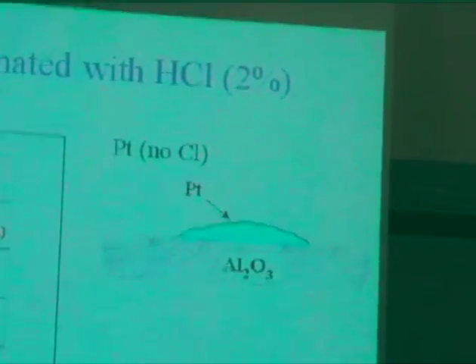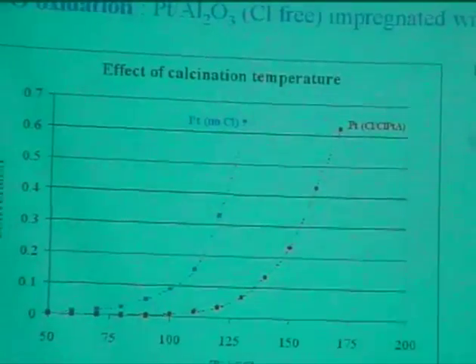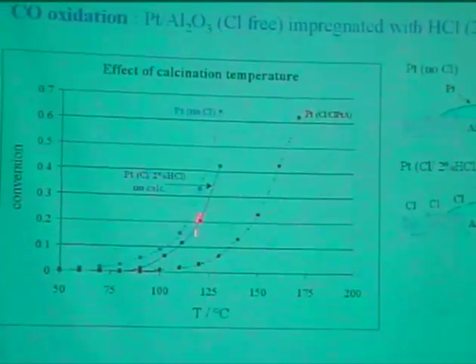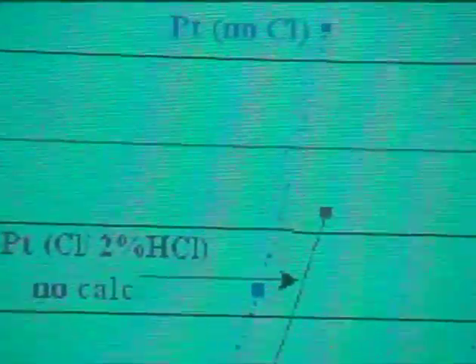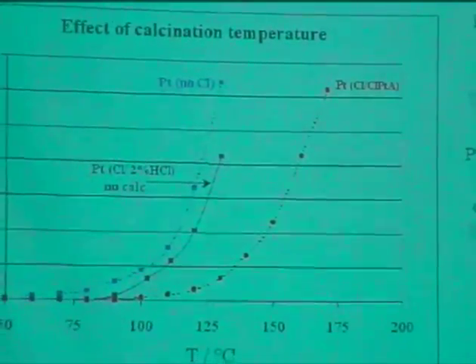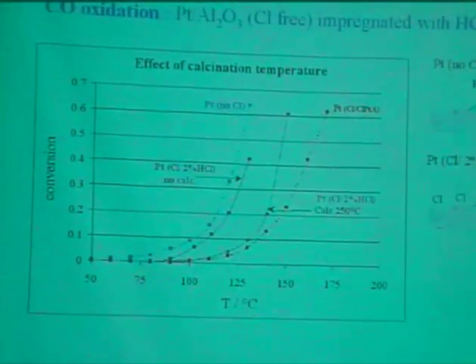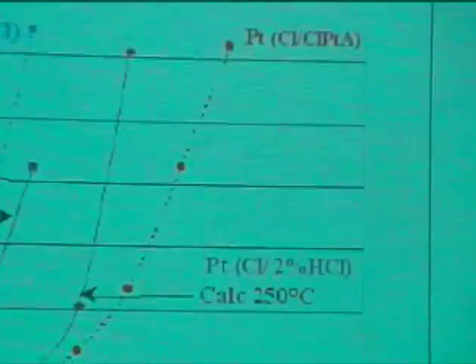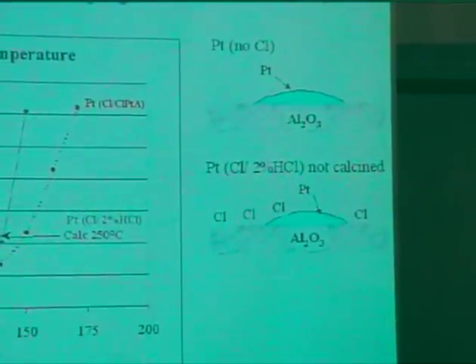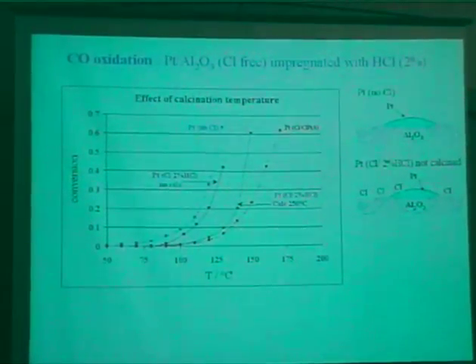Okay, now what we wanted to prove was to start with this catalyst and add chlorine to it. The catalyst without chlorine is pictured there with the cartoon. The first results that we obtained were sort of disappointing because they didn't show the effect as much. Here we added about 2% chlorine, and when my student didn't calcine the catalyst, it showed about the same activity as the no-chlorine catalyst. I said, well, something is wrong here, so why don't we calcine the catalyst? So this very same catalyst was calcined now at 250, and the chlorine that was hidden on the support, and this is very interesting because it's a very dynamic behavior of what's going on on the support and on the surface of the catalyst. Sure enough, it went back to the surface, and there you have a decrease in activity.